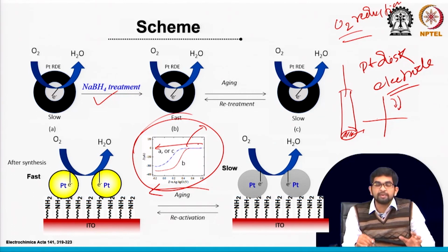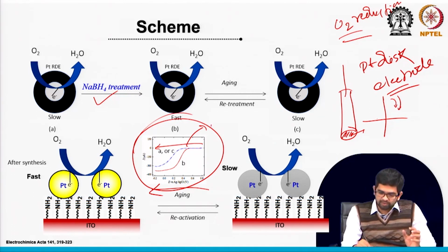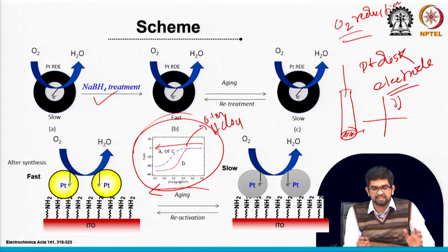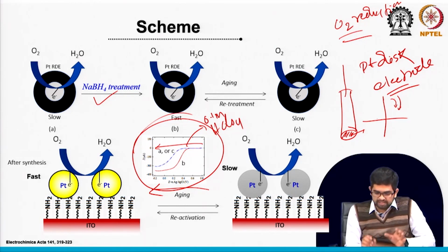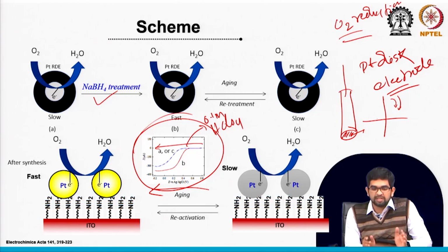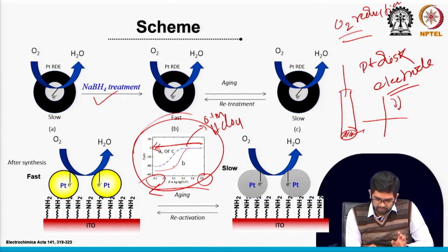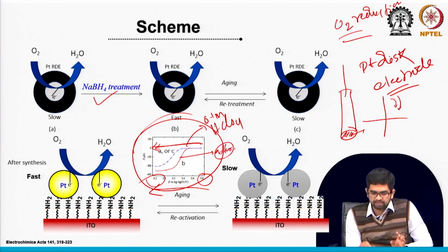For the measurement of the oxygen reduction reaction on platinum, we are using perchlorate solution, around 0.1 molar perchlorate. So, it is a little acidic, it is an acidic solution, and we scan the cyclic voltammogram from right to left, from 0.8 to minus 0.2. You can see this red one just after sodium borohydride treatment, and then this blue one, after the aging effect, maybe after 1 week.